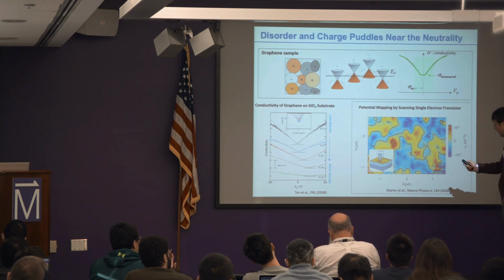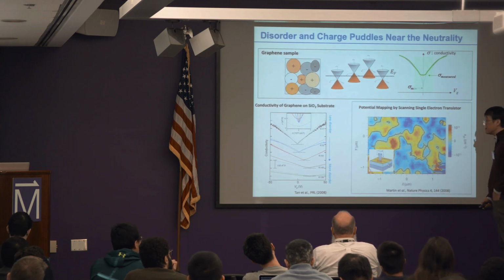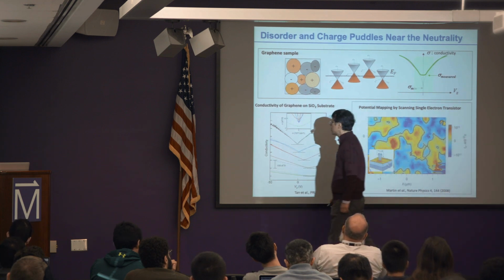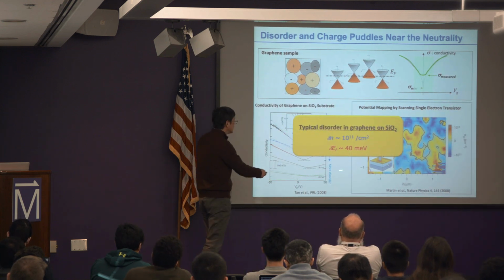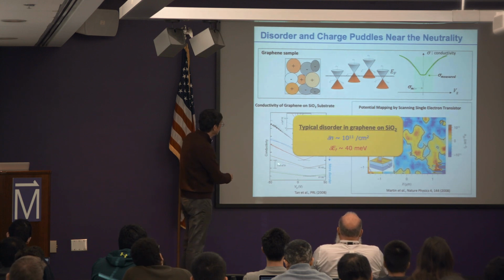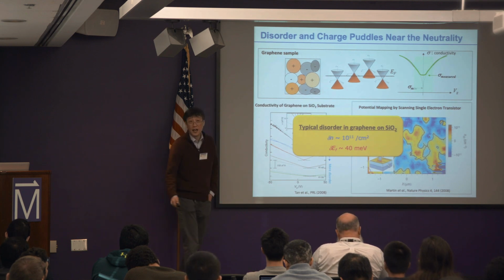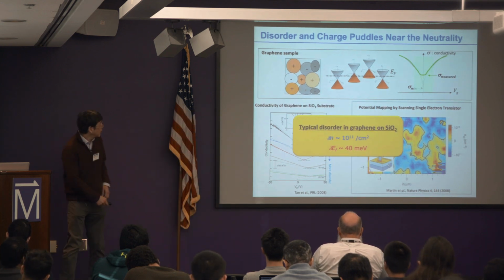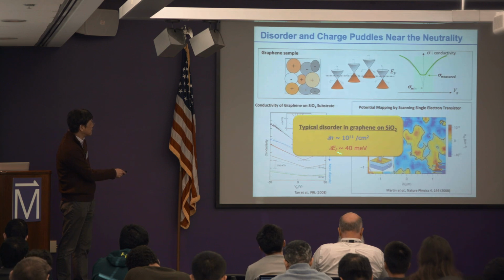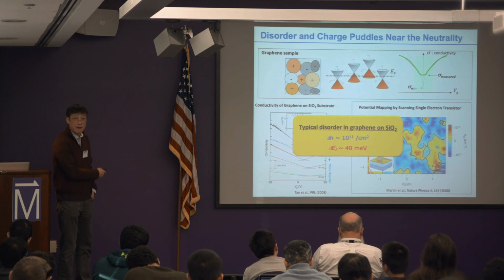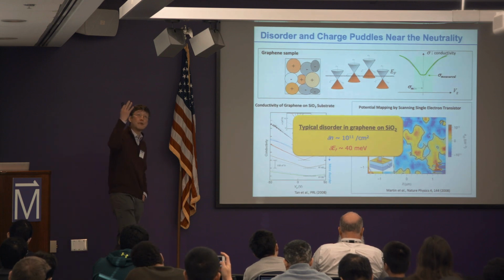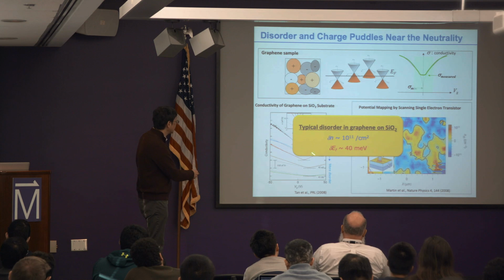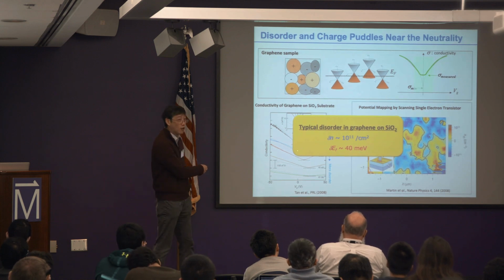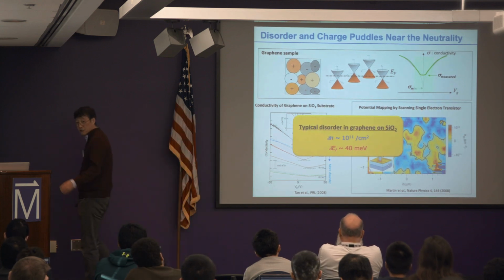What happened was that the samples got greatly improved after this. By the way, in these typical cases the electron-hole puddle density, the residual density, is about 10 to the 11 electrons per square centimeter, which relates to a Fermi energy modulation of about 40 millielectron volts. So in this type of sample, as you change the temperature from room temperature to low temperature, not much happens, because the disorder energy scale is already larger than room temperature.